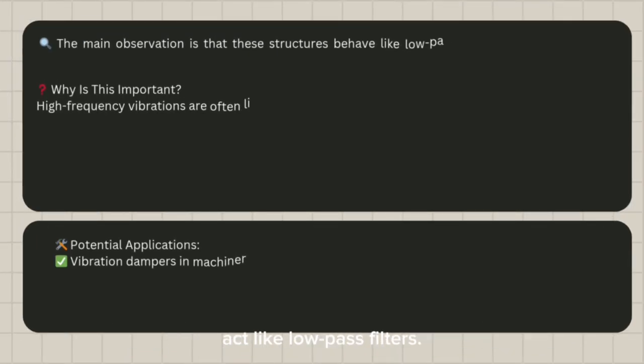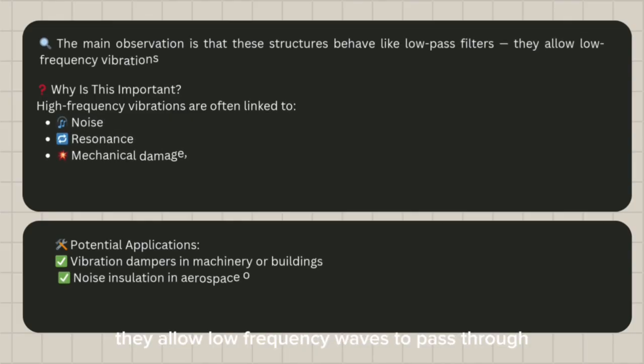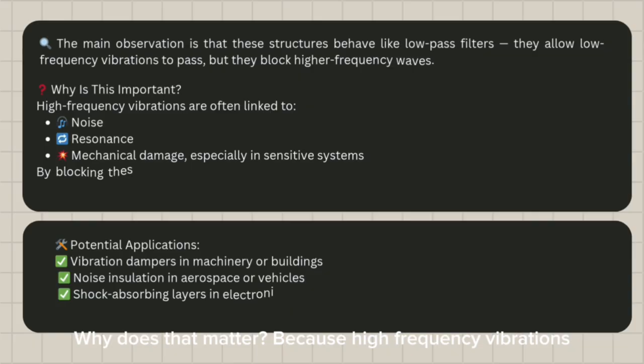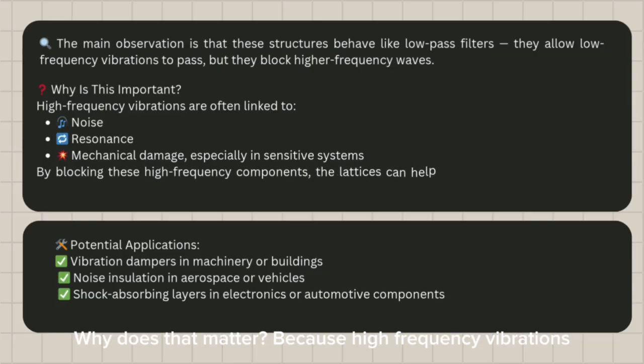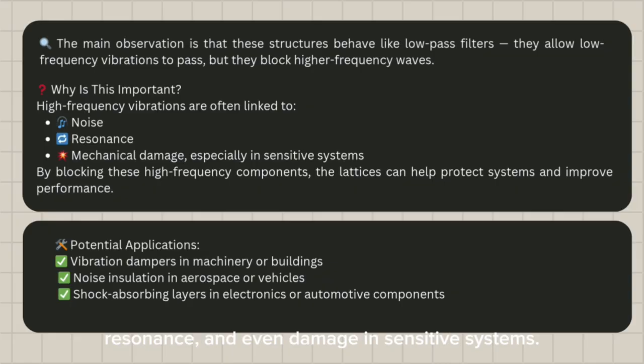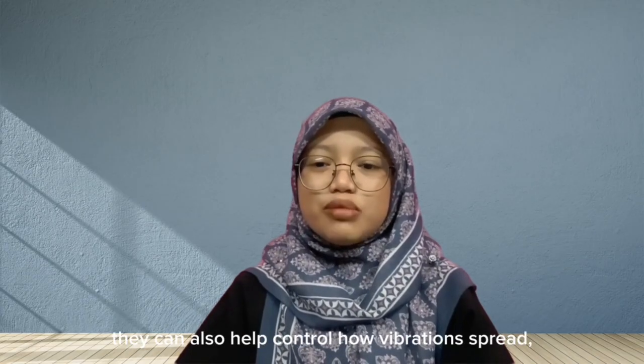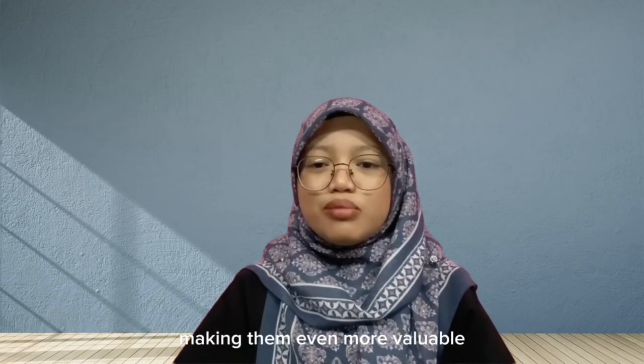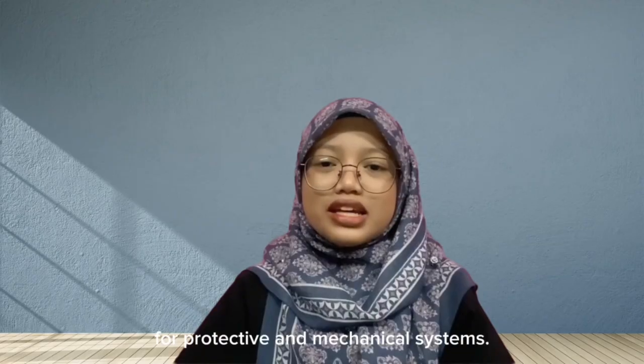The main finding here is that the lattice structures act like low-pass filters. That means they allow low-frequency waves to pass through but block high-frequency vibrations. Why does that matter? Because high-frequency vibrations are often linked to noise, resonance, and even damage in sensitive systems. By filtering them out, these lattices could be very useful in applications like vibration dampers, noise insulation, and shock-absorbing materials for electronics or vehicles. So this result shows that the benefit of lattice structures isn't just in absorbing force. They can also help control how vibrations spread, making them even more valuable for protective and mechanical systems.